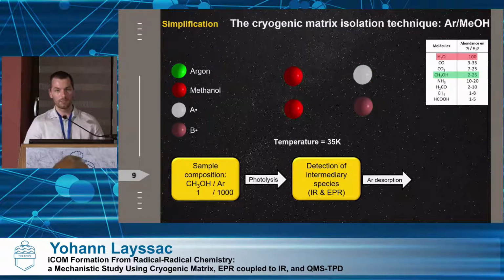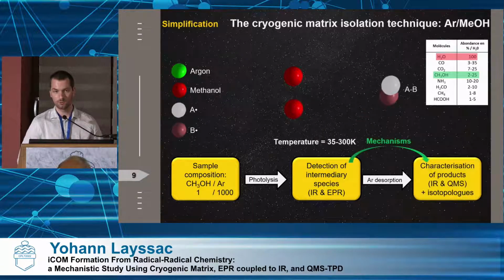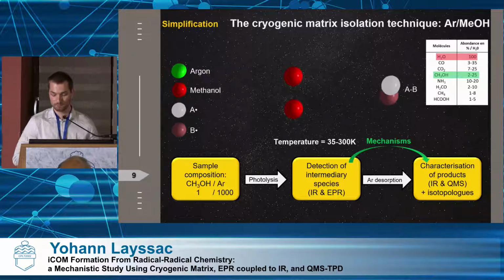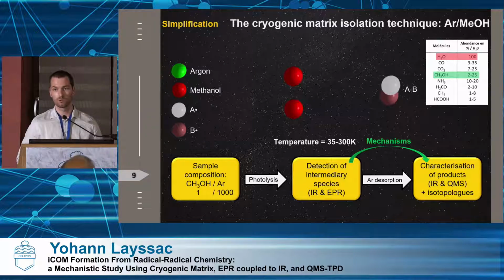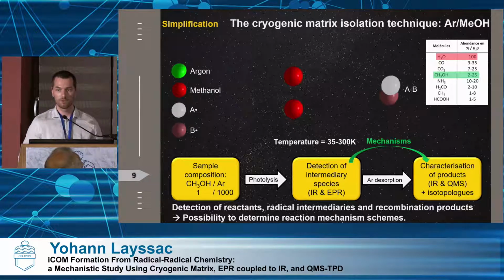The next step is that we dissolve the argon matrix by increasing the temperature to 35 K, so that now we don't have the cages that separate the radicals anymore, so they will diffuse into the solid film that is forming, to form stable products that we can characterize using infrared and QMS, just as I told you in the presentation of RING. Of course, we do a lot of isotopologue experiments also to confirm each attribution. And the final thing that we get is a complete scheme of the reaction, starting from the reactants, going through the products, and we also have the detection of intermediate species that allow us to speak about mechanisms.